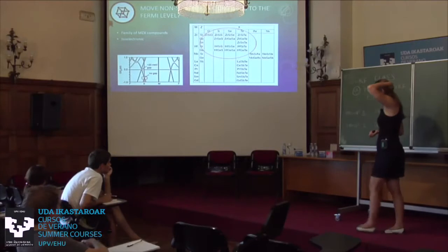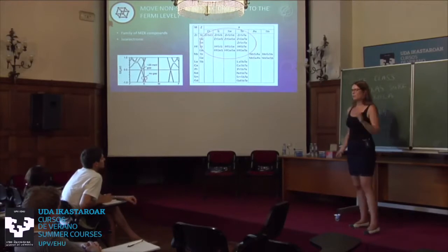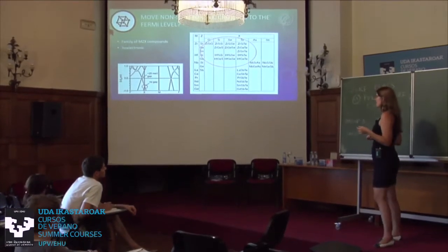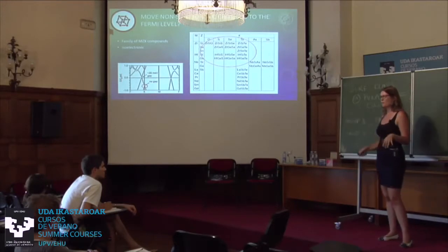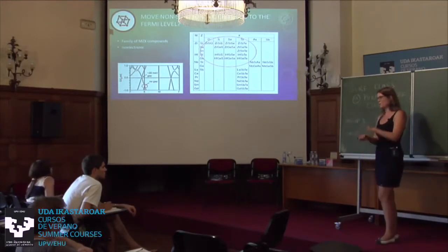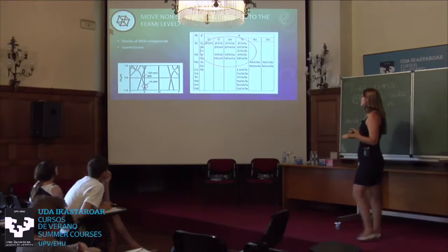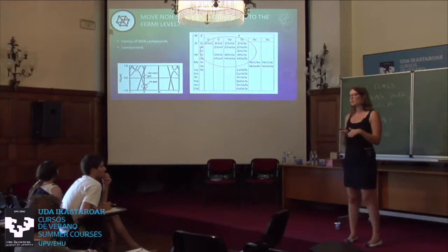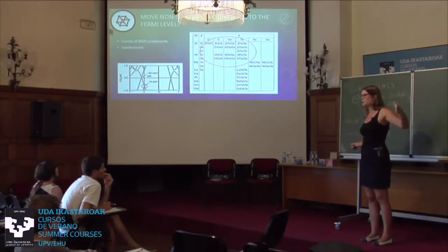So I thought maybe I can just trick the system and use a chemistry trick to modify the electronic structure differently. And often electronic structures are affected by strain or pressure. And a pressure or strain experiment to be done in reality is extremely complicated. And I don't know if you can even do an ARPES experiment on something which is under pressure because the photons go through diamonds and everything. So I thought maybe we use something which is called chemical pressure, which is actually a very common concept in chemistry, where you substitute an element with a different element which has a larger size, right? We were talking about the radius and the sizes before, and because this element is larger, it strains the whole material.